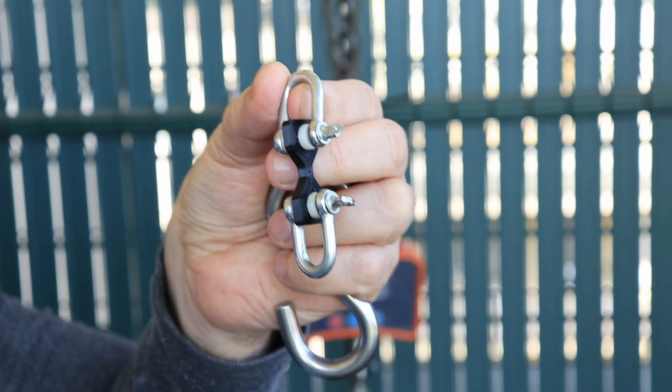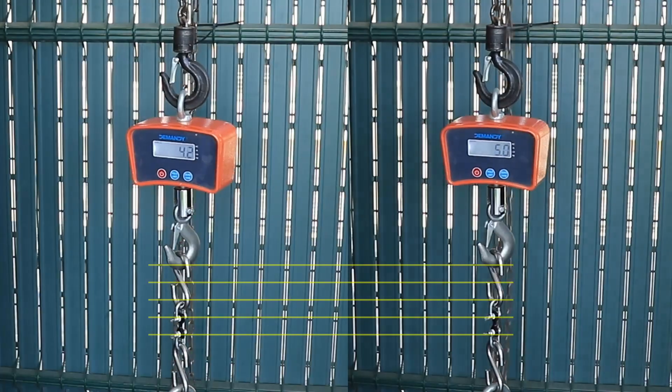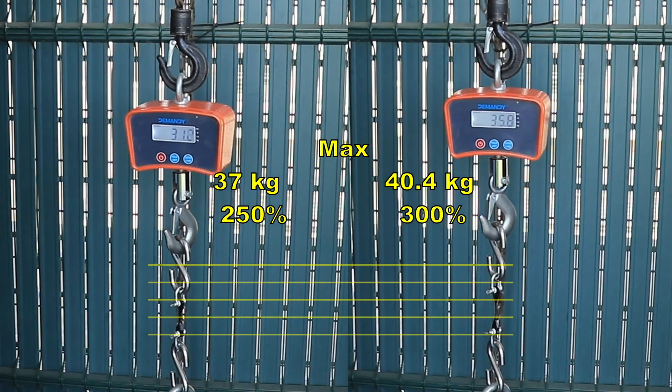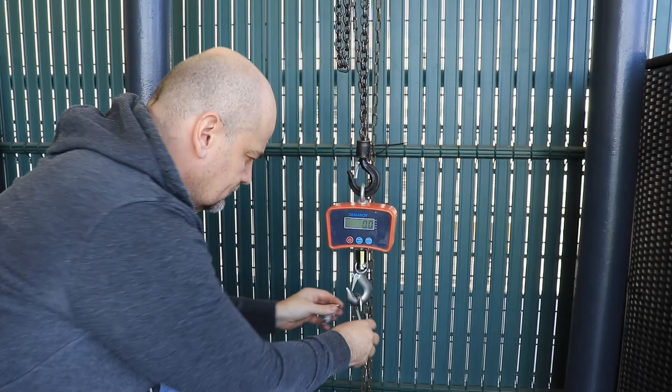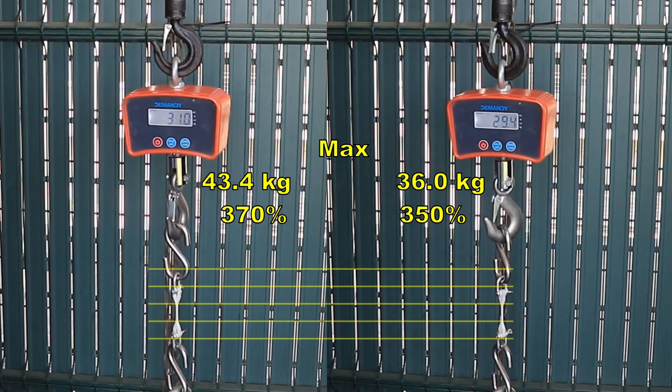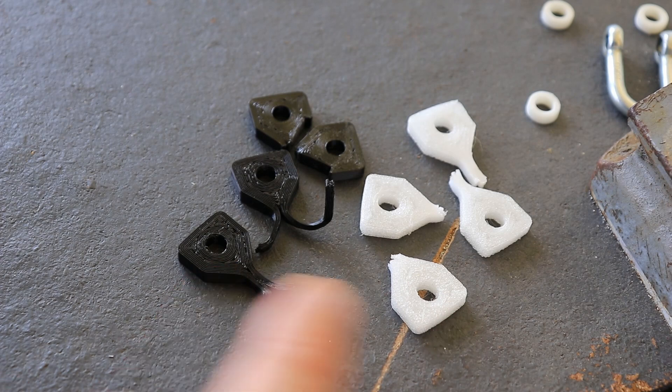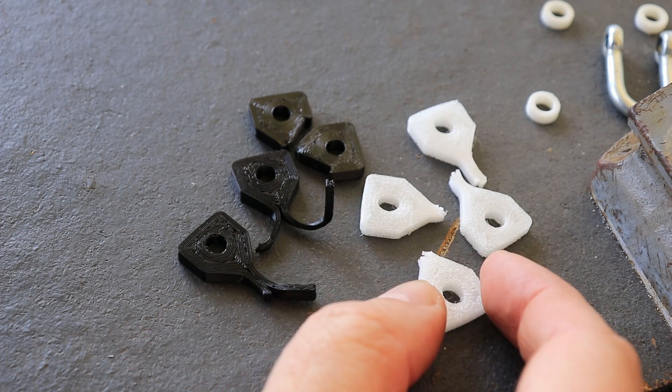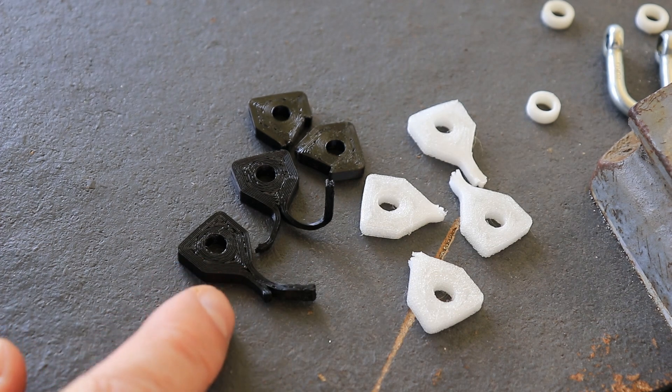I am starting with tensile or pulling test. The smallest cross section area is 4x4 mm. I am starting with regular TPU, and this is the antibacterial version. Well this break looks much healthier compared to this one so maybe this is a sign that antibacterial TPU has better layer adhesion but I will find that soon in the next experiment.